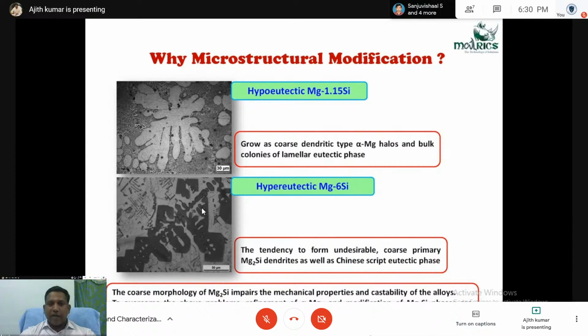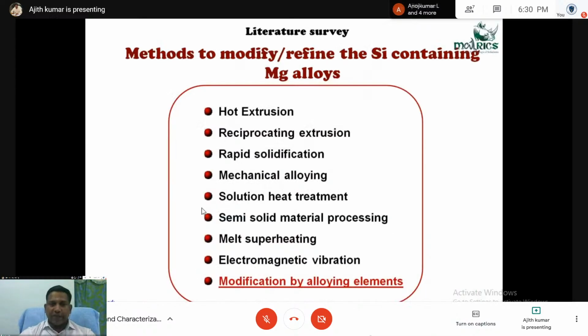This coarse morphology is the reason for reducing its properties. Because of this coarse morphology, the tensile property is reducing. So if we modify this morphology, we can improve the property. From the literature, we can understand that there are different modification methods, like hot extrusion, reciprocating extrusion, rapid solidification, mechanical alloying, solution heat treatment, semi-solid material processing, melt superheating, electromagnetic vibration, and modification by alloying elements. These are the different modification methods of magnesium silicon alloys to modify the structure. Then by the modification, we can improve the mechanical property or other properties.